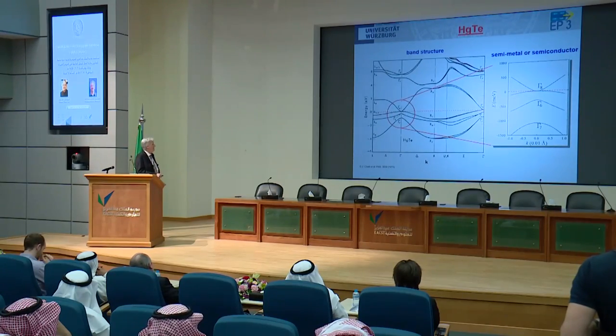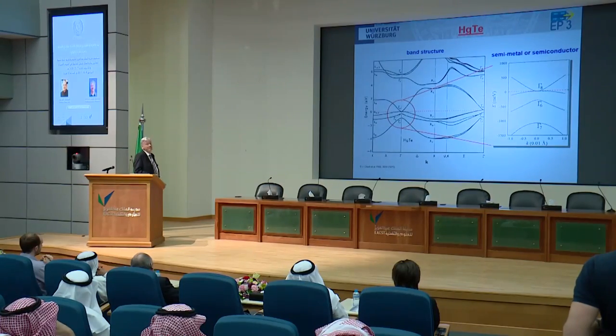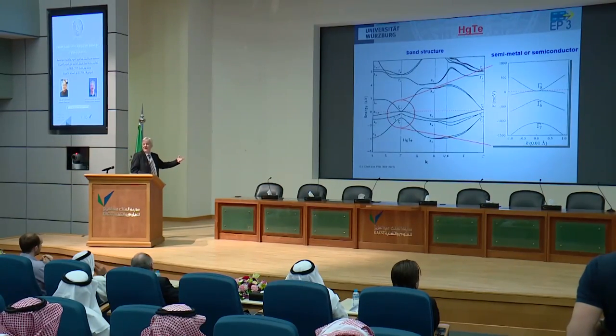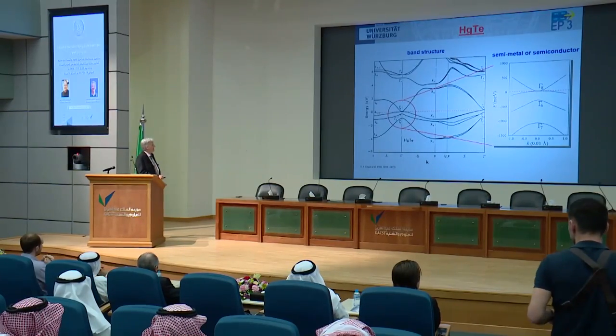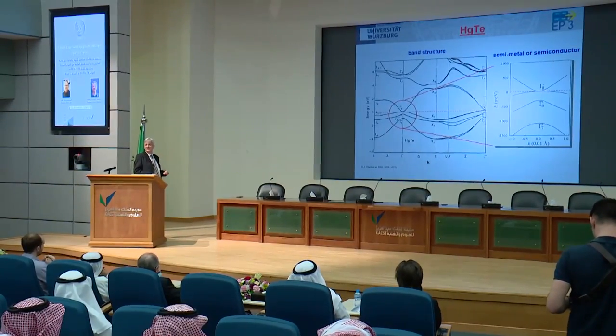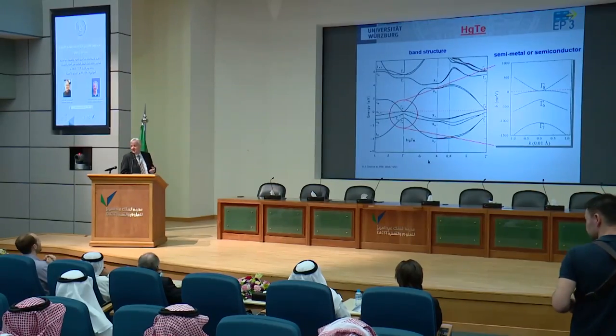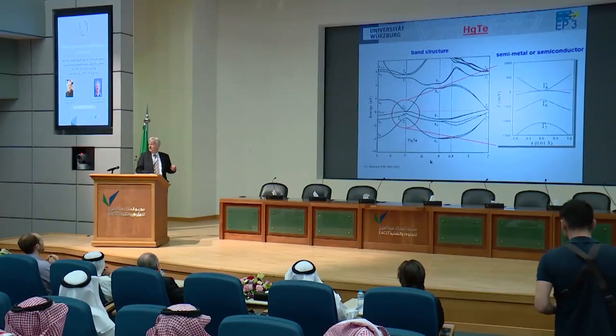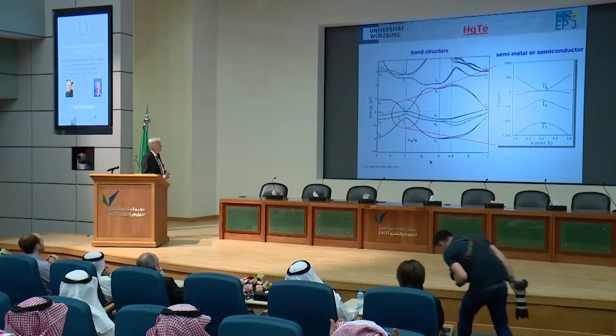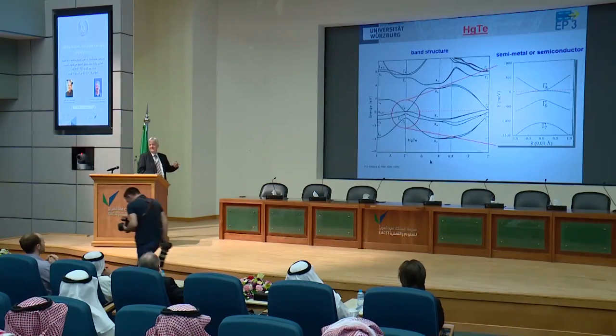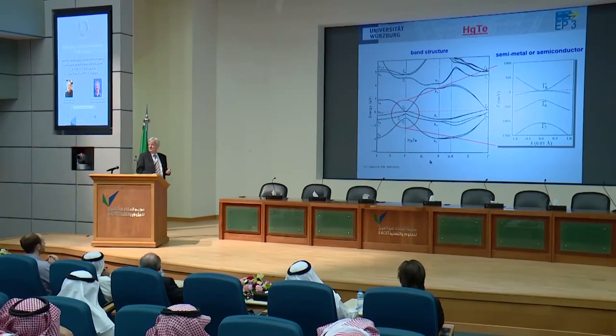So you have the heavy hole, light hole doublet, which has a gamma 8 symmetry, and a gamma 7 spin orbit band. These are normally the valence band states in your zinc blende semiconductor. The weird thing is this one here, gamma 6. Gamma 6 usually is the conduction band, and it comes from unoccupied s orbitals of the metal. And so there's something weird going on here, and the reason is that the metal in mercury telluride is mercury.